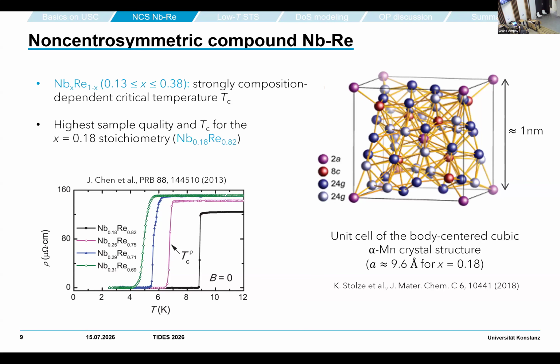Niobium-rhenium is a compound which, in a certain ratio of niobium mixed into rhenium, crystallizes in a very particular crystal structure, the alpha manganese structure—a very complex one with 58 atoms in the unit cell.